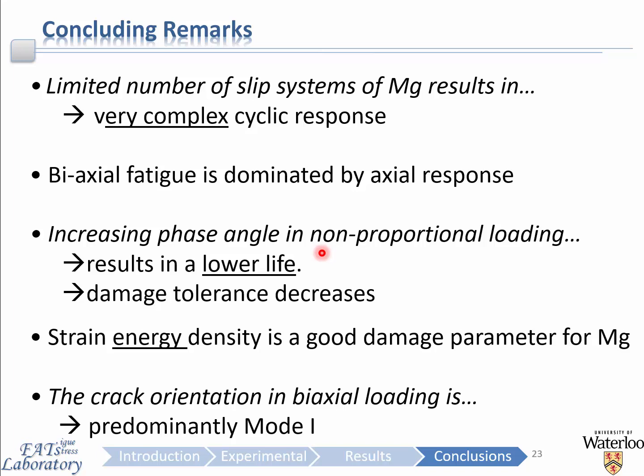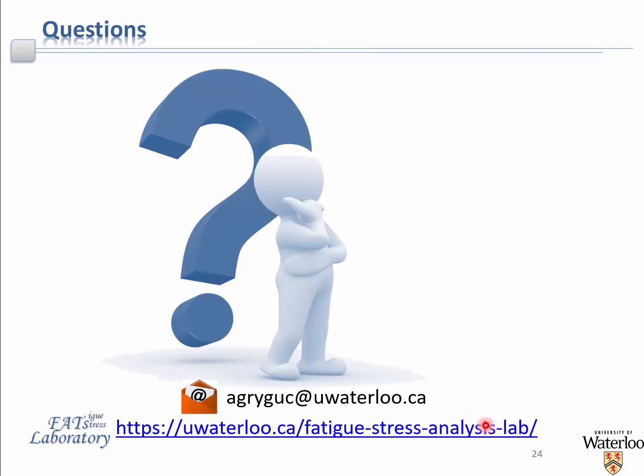Strain energy density is a good damage parameter for magnesium because it's a scalar quantity that is invariant of the material direction. So this is something that was demonstrated to be quite robust and convenient with asymmetric and anisotropic materials such as the forged magnesium that we have investigated here. Finally, the crack orientation in biaxial loading is dominated by a mode 1 crack that is perpendicular to the loading axis and does not resemble the crack observed in the pure shear case.